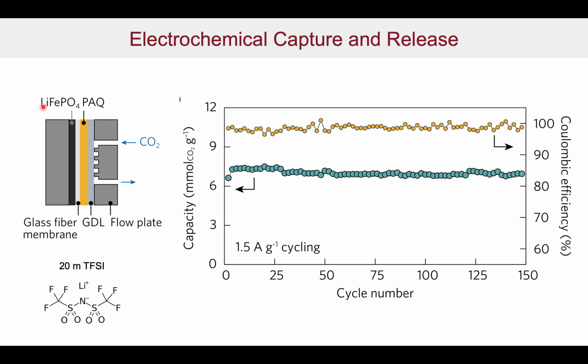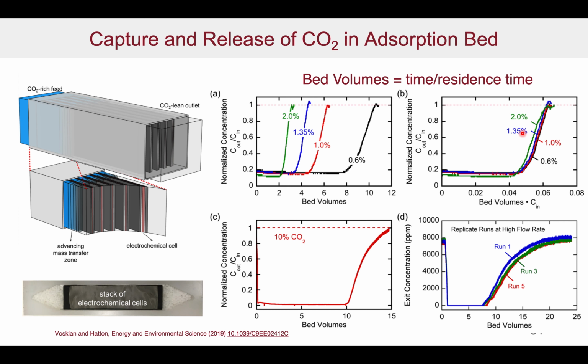In this case, we used a different cathode electrode, a lithium iron phosphate electrode, all in an ionic liquid. An important part about this is that the overall working capacity of the system did not vary over about 150 cycles, as shown here, and our coulombic efficiency was really high in this particular case, close to 100% for the most part, which is really encouraging.